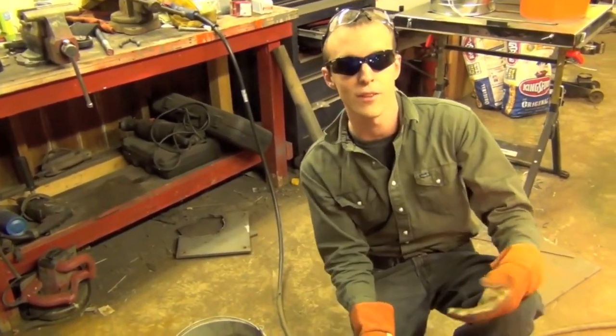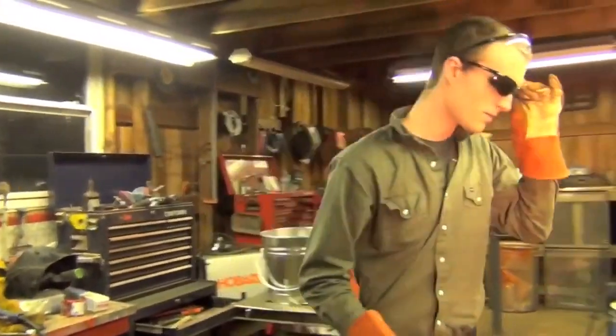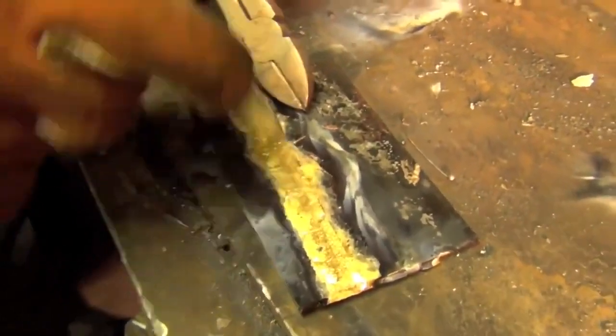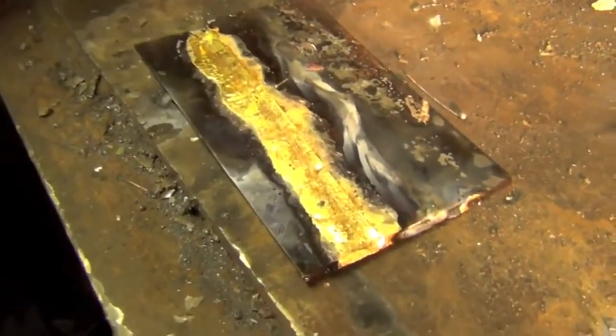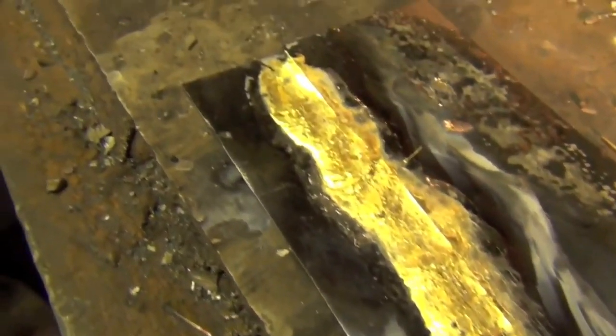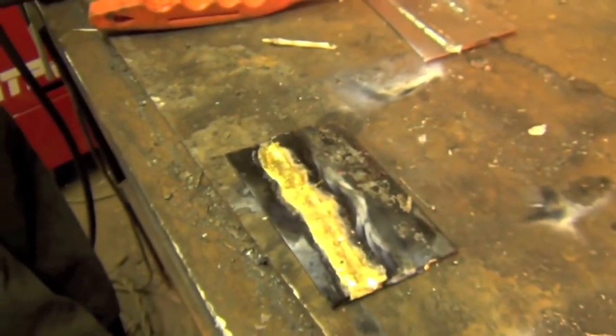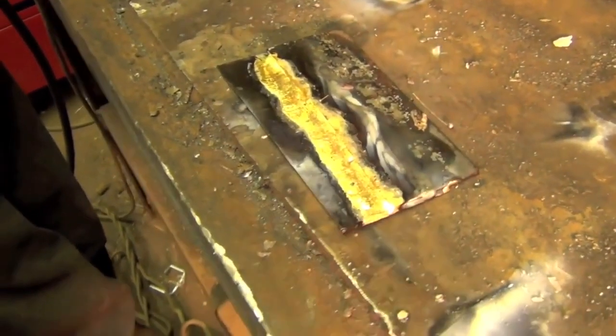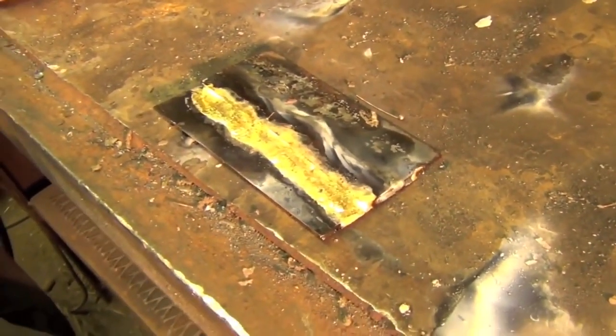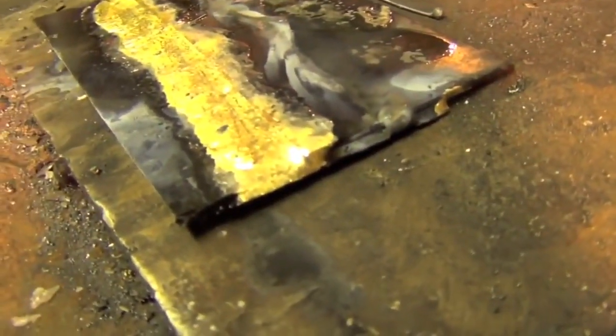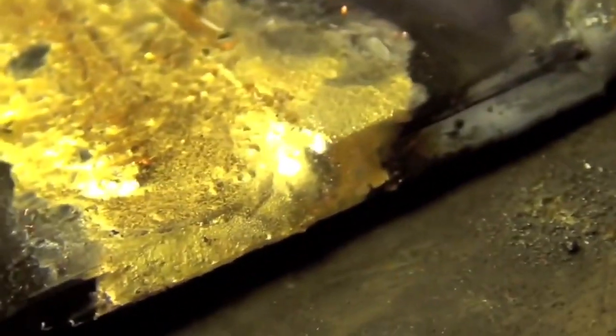That right there alone popped off a lot of that glass-like substance and the rest is going to come off a lot easier. I remember learning in high school that as soon as you're done welding and you go to chip your slag, if it's still hot, it's still soft and you're just banging on it and it doesn't really come off. Your best bet, I know you can take it off while it's still hot, but if possible I like to cool it down first. Let's see how we did. Well, it appears I have some holes in mine. It's just kind of a little bit everywhere, but it's brazing in all of its glory. With braze, you don't have a real fast forming puddle like with steel. You've got that heat kind of spread all over with the torch, so it's hard to get this ripple look. I don't really know if you even need the ripple look because it's more about getting it to draw in between the two plates. You can kind of see here on the end where it's started to suck back up underneath there, which is what you're after.